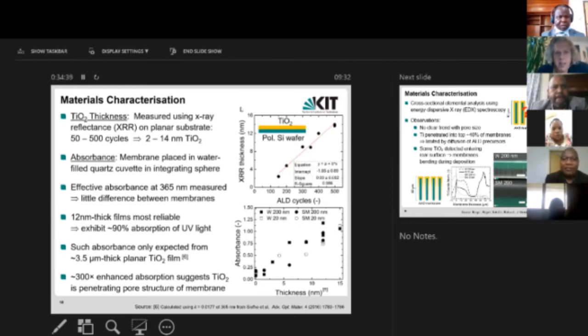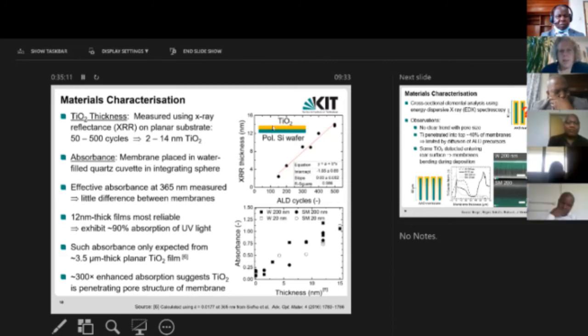But the problem here is that we're not always sure of the exact chemical nature of the films. So whether they are fully anatase or still partially amorphous, or perhaps if you go to higher temperature, you will get rutile present. There you might get a mixture which would cause problems with your refractive indices. So by using X-ray reflectance, which is like X-ray diffraction, just in a modified geometry, we're just looking at the elements as they're stacked up in the planes, and then getting information about that.